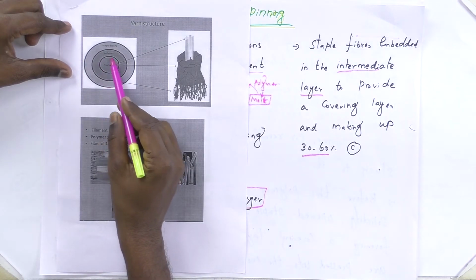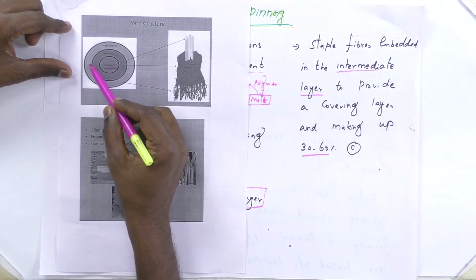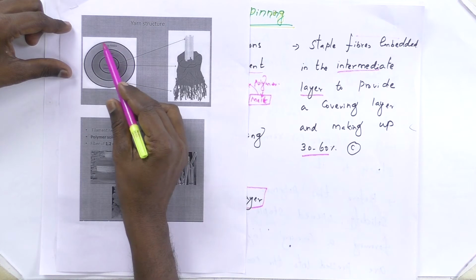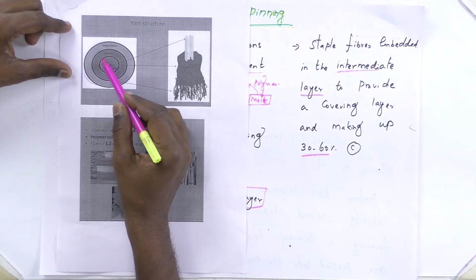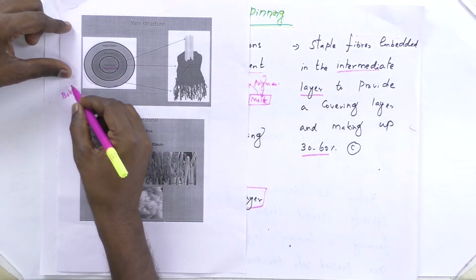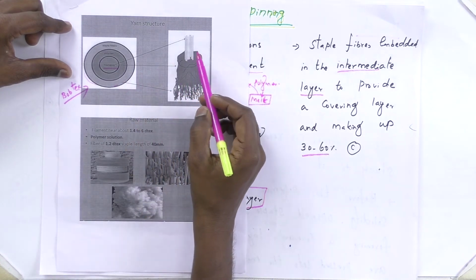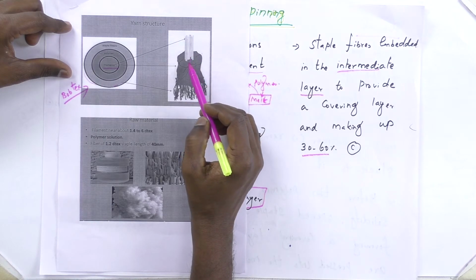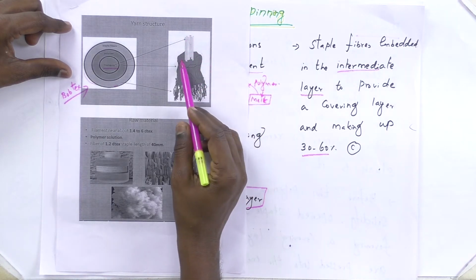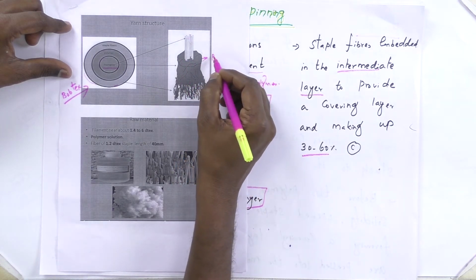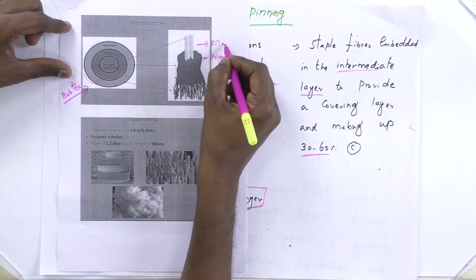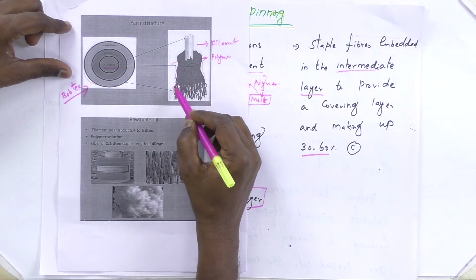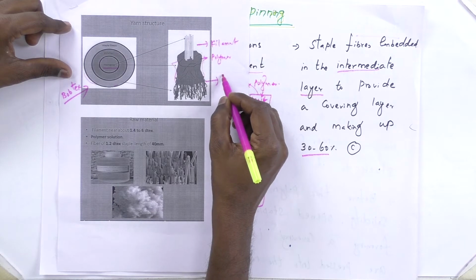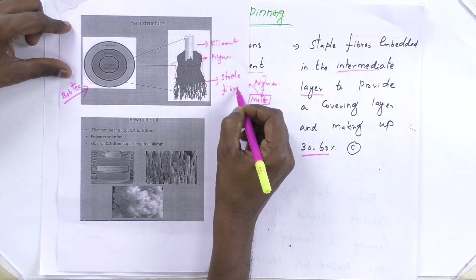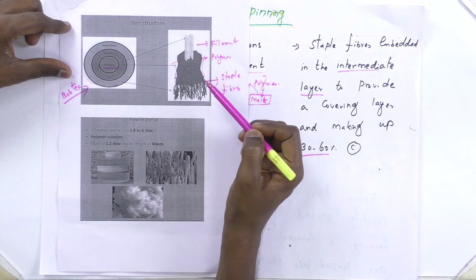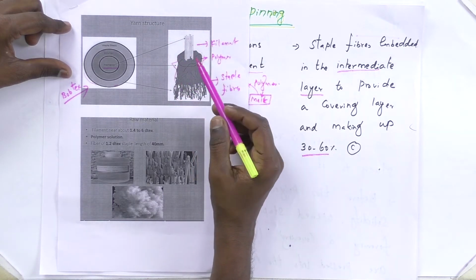The center core is a filament yarn. Here the intermediate layer is a polymer solution. The outer is embedded with fibers. This is the cross-sectional view of a Bobtex spinning yarn. So this is a longitudinal diagram. The filament is in the center of the yarn like a lumen in the cotton fiber. Then the intermediate layer consists of polymer. This is polymer. This is filament. The surface of the polymer is embedded with loose fibers or staple fibers. So these 3 components, the filament, polymer and staple fibers on the surface, jointly produce the Bobtex spinning yarn.